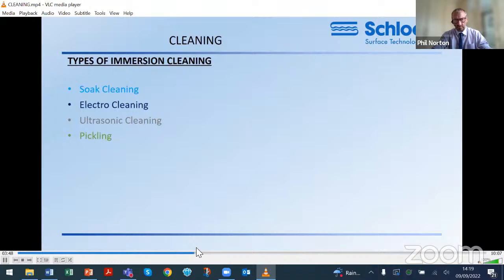Electrocleaning is widely utilised for metal surfaces and involves passing a current through the surface to be cleaned. This generates a lot of gas on the surface, which has a type of scrubbing effect. The polarity and strength of the current can vary dependent on the metal being cleaned. Ultrasonic cleaning uses high-frequency sound which induces cavitation bubbles on the surface, which in turn dislodge contaminants. You can normally hear a very high-pitched screaming sound during this process.